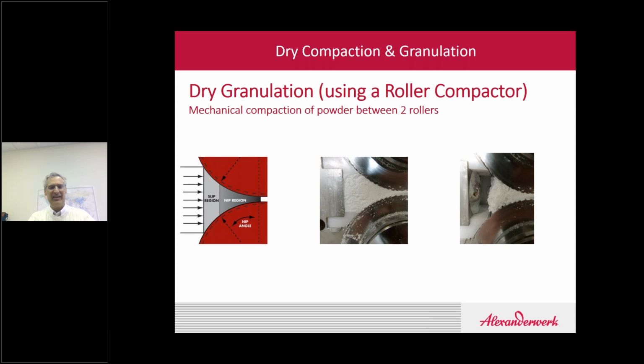The powder, as you can see, is getting compressed, and you can see directly there is a very definitive line of where the powder has actually started to compress into the flake form. And that's where that region is, which transfers from the slip region into the nip region. We'll talk more about that in the upcoming slides also.